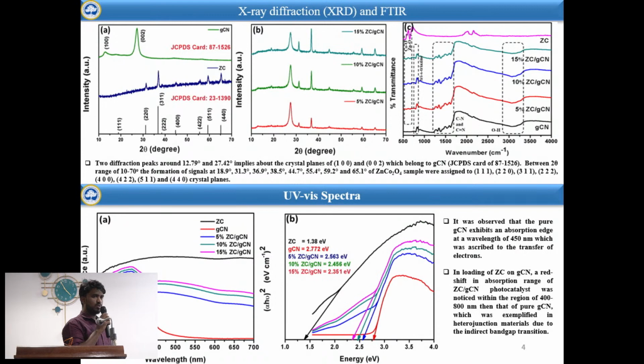And figure C shows the FTIR analysis with respect to the formation of functional groups over the material. In the range of 500 to 1000, we can notice the presence of cobalt-oxygen bonds as well as zinc-oxygen bond formation, which is referenced with the pure zinc cobalt oxide FTIR. And we are able to see the tri-s-triazine group of graphitic carbon nitride in the range of 500 to 800.